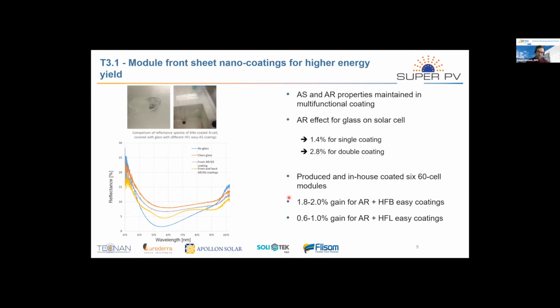And then Luredera also applied this solution to real 60 cell modules provided by SoliTek and Apollon. And here they measured a gain of 2% max for the AR and HFB coating, and a slightly lower gain of 1% for the AR and HFL coating. And currently these modules are tested in our outdoor test sites in Super PV. We have 6 outdoor test sites, which will be presented tomorrow by my colleague Julius De Navas. So stay tuned to get results on this tomorrow.